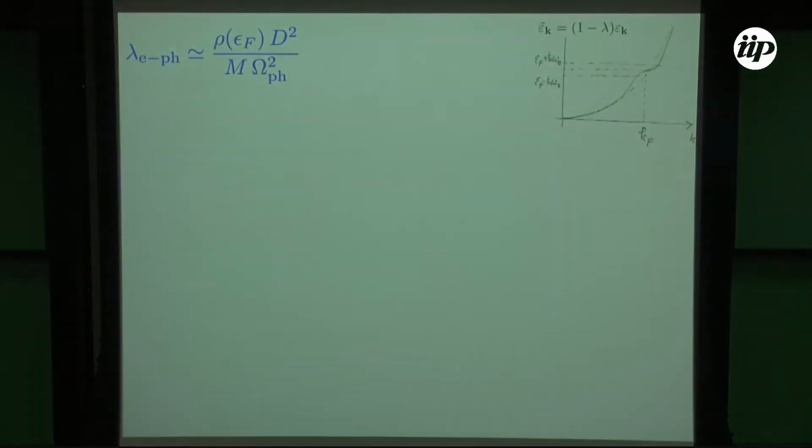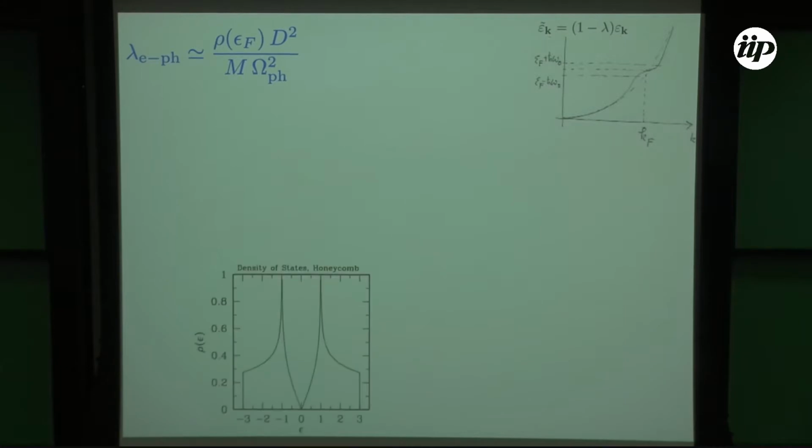And basically, the reason for that is that if we want to make a graphene superconducting intrinsically, then we would like to have this quantity to be as large as possible, which we can do if we maximize the numerator and minimize the denominator. So one thing for that would be that we are talking about the density of states of the electron, and the pi electrons in graphene, basically they are vanishing around the zero. So one way would be let's try to have a high doping. So this would really definitely help, because we will get these things larger.